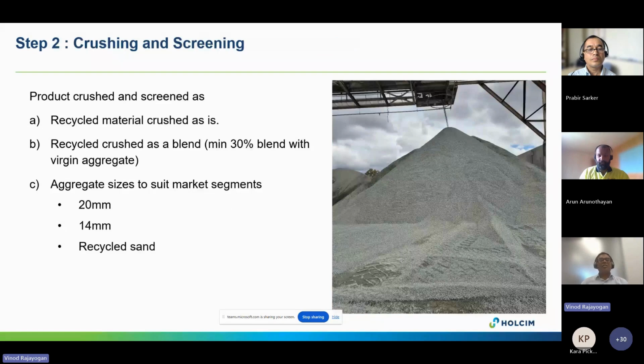The product was then crushed and screened. We have gone through different iterations of the process to crush and screen. We started off initially with just crushing and screening without any curing. We then put in a process to cure it for a period of time before it's crushed and screened. We then moved towards blending with virgin aggregates to reduce variation as well. And in the current market, over a timeline of let's say 5 years, we've now implemented 3 product streams we've been creating from this recycled material: 20mm and 14mm aggregates, and recycled sand.